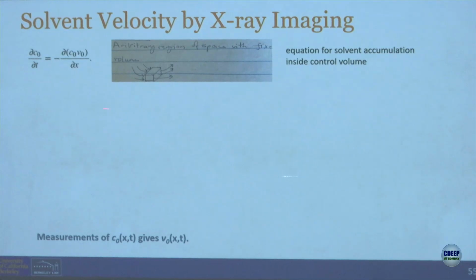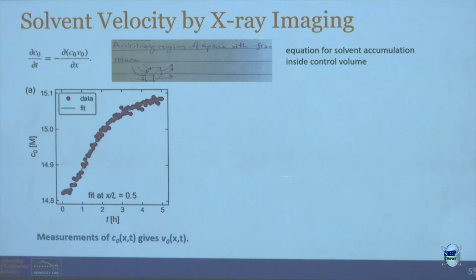conservation, right? The solvent accumulating in the little control volume has to be carried in, and because it's one-dimensional, it's in the x direction by the velocity. And so if I know C0 as a function of x and time, I get solvent velocity as a function of x and time. And so taking those data I showed you in the previous slide, and this is at the middle of the cell.